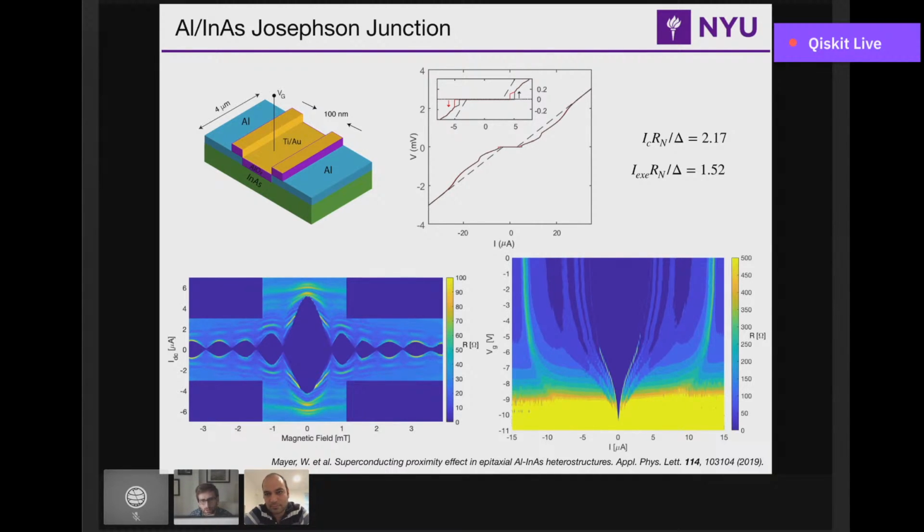I see. And so in the current-voltage diagram here, you have the nice superconducting state, and then you have several... It almost looks like a step, I guess. Do we know what that is? Yeah. So some of those are MAR, multiple Andreev reflection. But because we are usually doing current bias, it's very difficult to actually associate them directly in voltage. But there's a paper from 2016, I think, that actually studies this, and it seems they're related to multiple Andreev reflection.